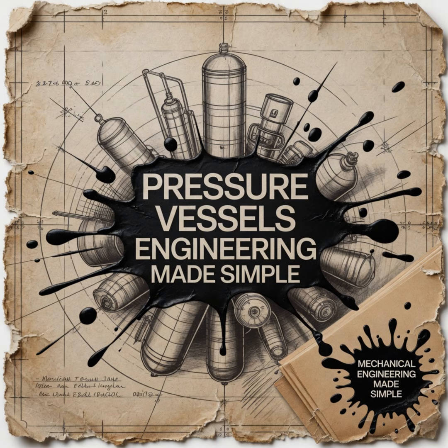Yes. That is why the tolerances for misalignment are incredibly strict. The code might dictate that the offset cannot exceed the thickness of the plate divided by 10, up to an absolute maximum of maybe 5 millimeters. And if the fit-up is worse than 5 millimeters? The inspector halts the job. You have to cut the tack welds, hook the plates back up to the cranes, use massive hydraulic jacks and strong backs to physically force the steel into alignment, and try again. You cannot bridge bad geometry with weld metal.